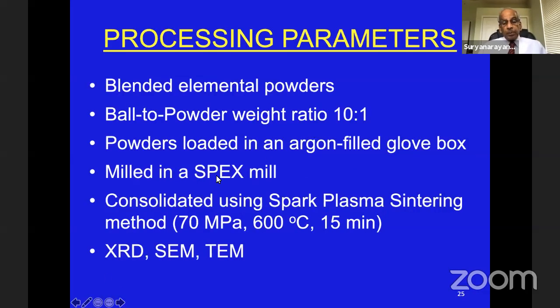These are the process parameters. We started with a SPEX mill, very low ball to powder ratio, but then we consolidated these materials using spark plasma sintering at relatively low temperature, 600 degrees C, just for 15 minutes, and using a relatively low pressure of 70 megapascals. But we were able to get complete densification.